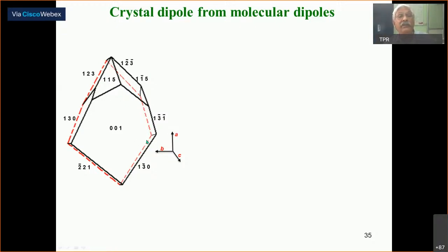sort of a picture that you can derive by looking at single crystal face indexing, because basically you try to figure out the face indexing by mounting a crystal in a single crystal diffractometer. This is a slightly large hopper crystal, and it's sort of fitted to the various Miller faces, and there's a crystallographic axis. And one important point that we understood from here is that this basal plane is essentially the 001 plane. That means the c-axis is perpendicular to this basal plane. And there are a lot of complicated Miller faces here.